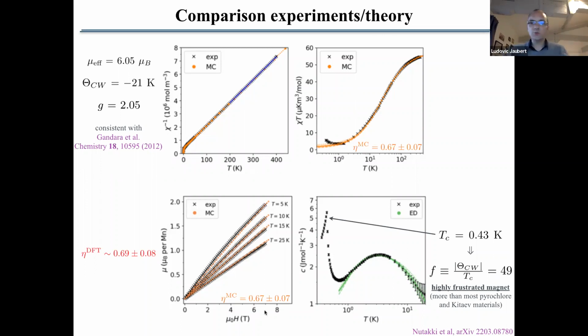And in addition, we try to calculate the specific heat. So we cannot use classical Monte Carlo for specific heat because the entropy is ill-defined in continuous classical spins. So we cannot calculate the specific heat properly. So we did a very rough approximation with exact diagonalization. So it's a non-controlled approximation. But with playing with J1 and J2, we could estimate the value of eta, and we found something of the order of 0.6 actually, 0.57, 0.6, which reproduces this bump here of the specific heat.